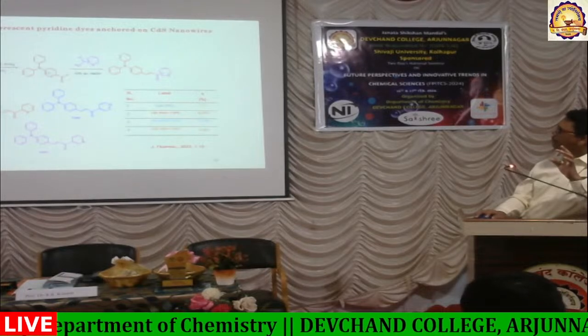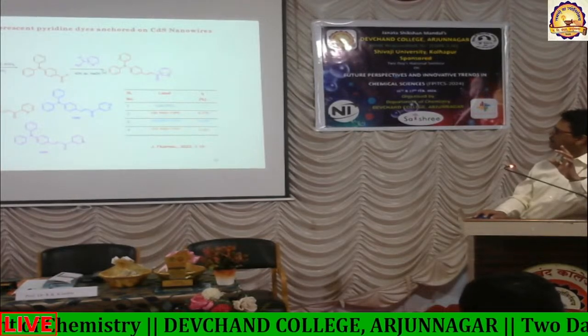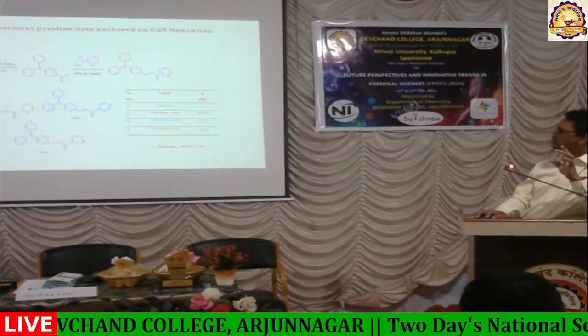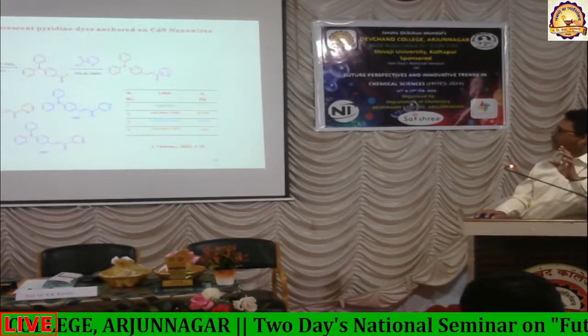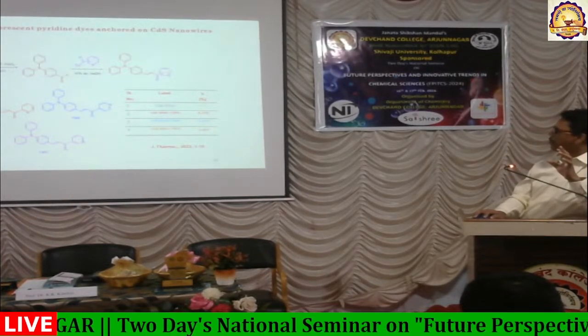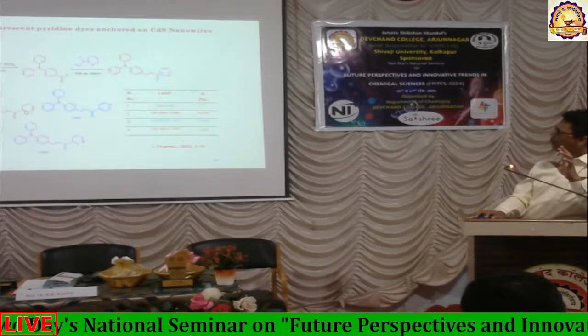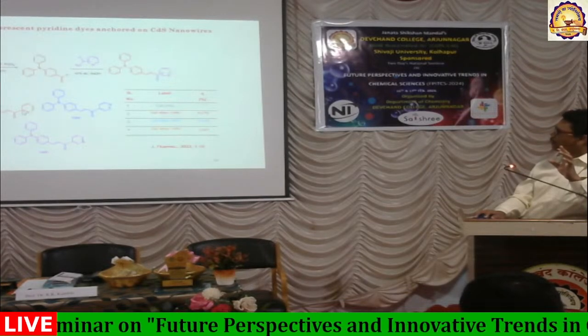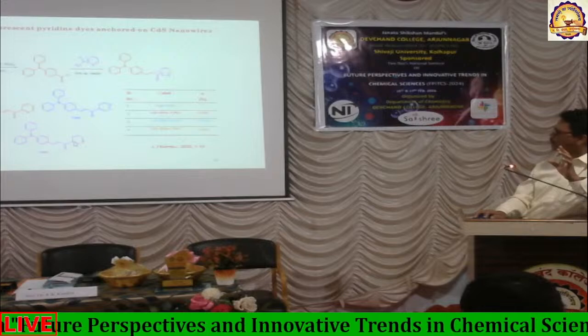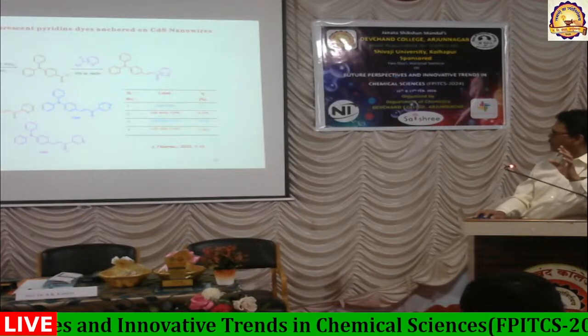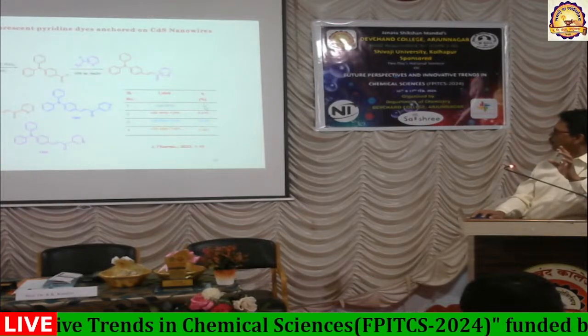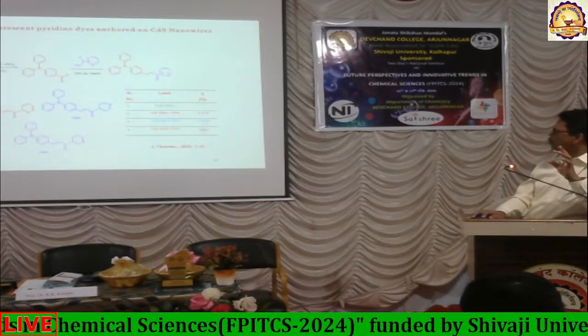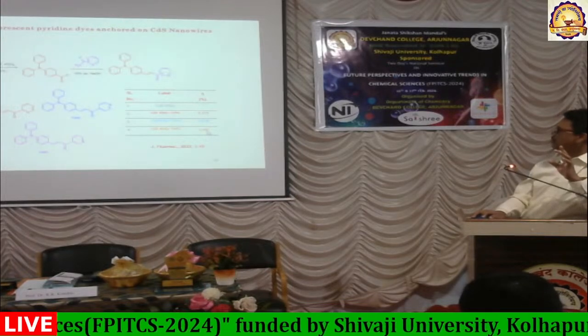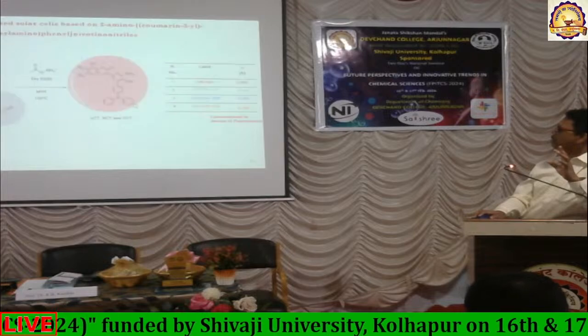These are also metal-free fluorescent pyridine dyes anchored on CdS nanowires. It's a very simple strategy where a simple triphenyl group was used along with pyridine at different positions: here it is at the 2nd position, here the 4th position, and here the 3rd position. Here also we observed more than 2 to 4 times increased efficiency.